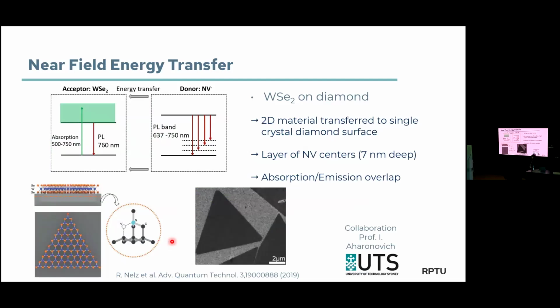No, actually we don't, because in this case you have to keep in mind we're in a solid at room temperature. So all the resonances are very broad. These optical resonances are not reacting to the magnetic field. So I would say it's more or less decoupled. You have the optical response and the magnetic response, and they are not really coupling. You can use them both independently, so to speak. You're not shifting anything out of resonance. Yes, the spin resonance shifts, but the optical resonance still stays where it is.